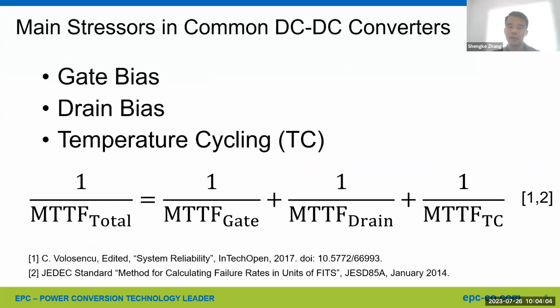For DC-DC converters, we identified three main stressors, which are gate bias, drain bias, and temperature cycling, TC. All three stressors are critical and affect the total lifetime. So the question is, how can we quantify the impact of each stressor towards the total lifetime? We developed this equation to quantify the influence of each stressor. Basically, the harshest stressor, or the one that gives you the least lifetime, dominates the overall lifetime.